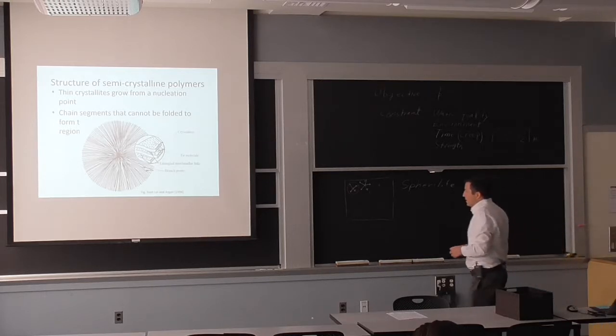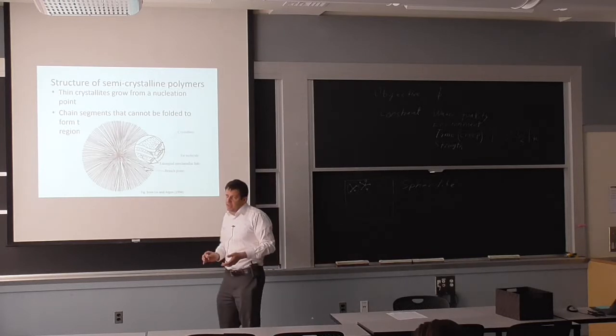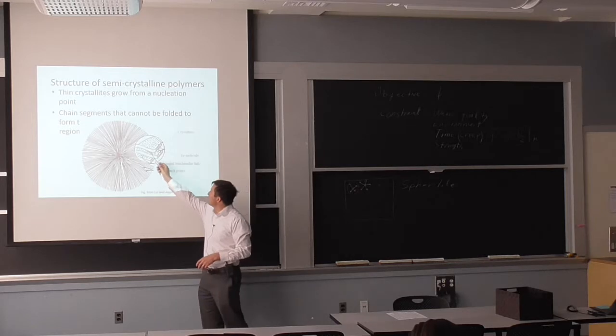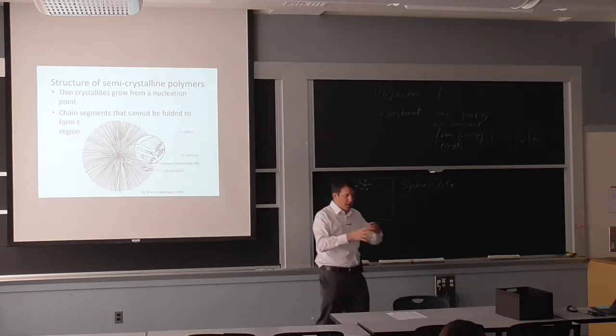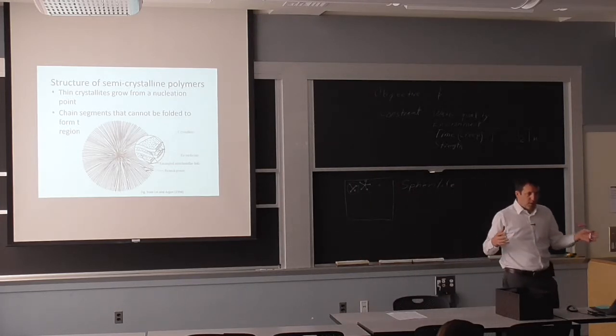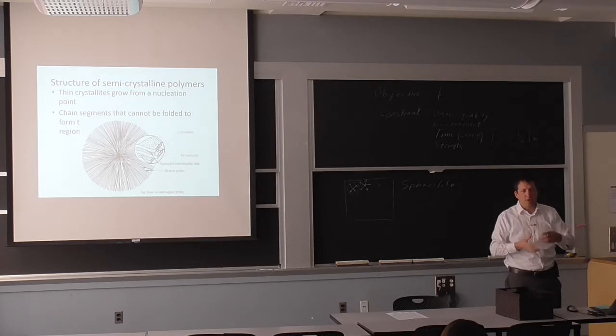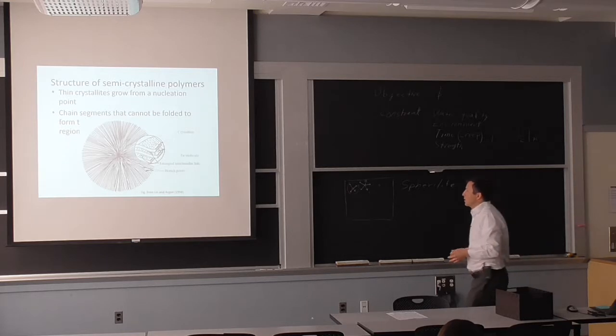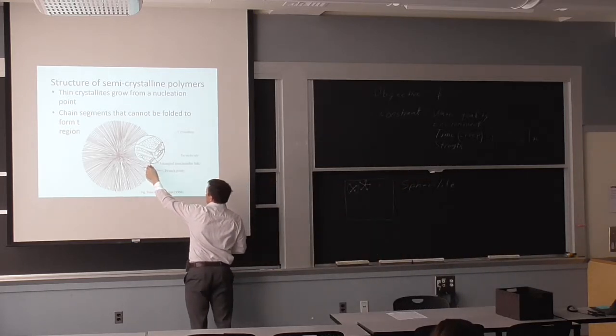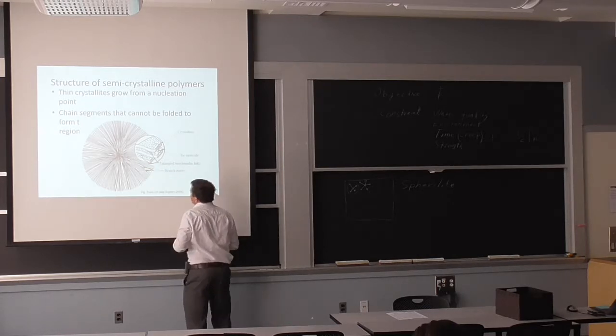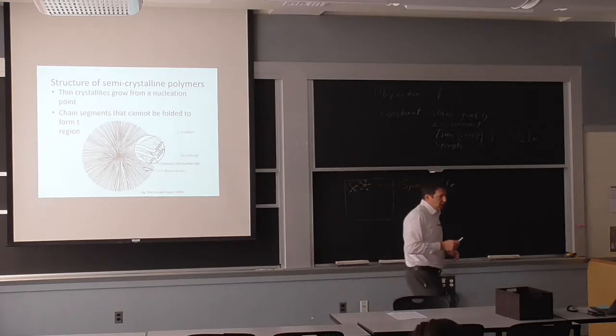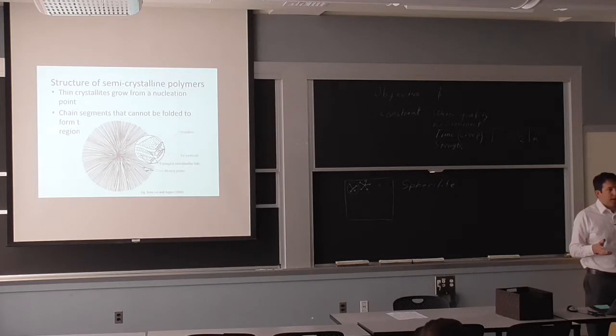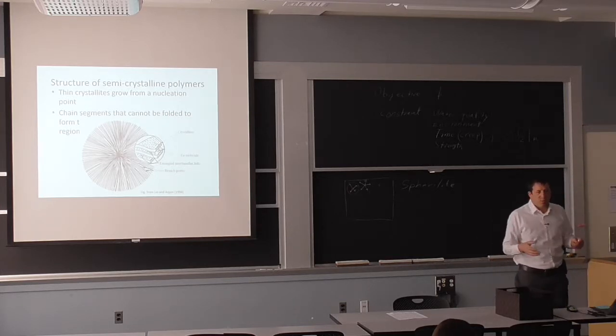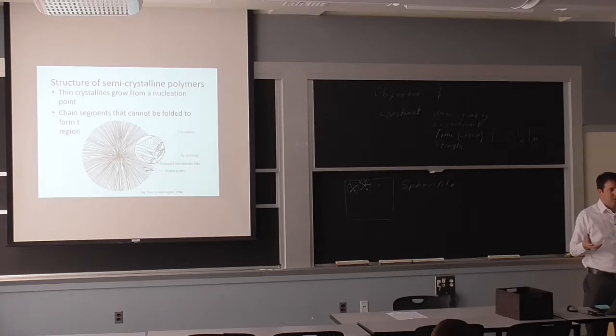It's not a simple cube like you probably heard for a lot of metals. Now, what's special here is virtually any structural polymer is going to have some amorphous zone, just because it's impossible to organize all these chains and just form crystal. There's going to be some entanglement. There's going to be some chains that are mixed that are not really able to crystallize. So you have a stacking essentially of the crystalline phase, the crystallites here, and then you intermix it with a little layer of amorphous structure. Now, it doesn't always happen that way. If you put nanoparticle, for example, you can change this behavior. Instead of starting from a point, perhaps it's starting from the particle and it's going all around. But the concept that you can't really organize the entire polymer chains into crystals remains the same.